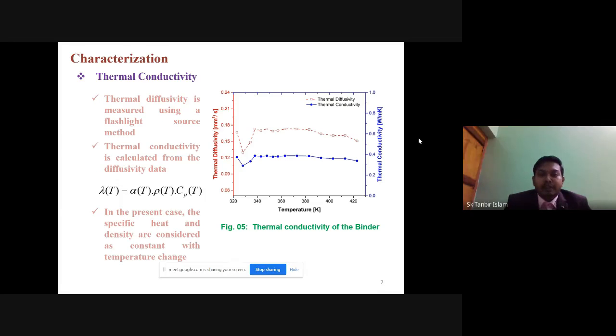Then thermal conductivity measurement. In this case, we have used the flash light source method to measure the thermal conductivity of the binder for a wide range of temperature. During our injection, the temperature falls from higher to lower. That's why we measure this in that way.